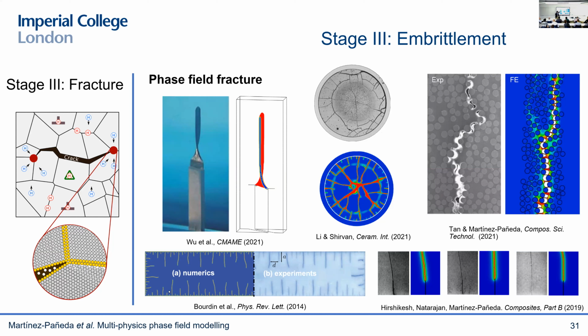You can see here multiple examples, some from my group, some from other groups, where very complex cracking phenomena can be captured and show a very good agreement with experiments. And we have had quite a lot of fun through the years working on this. So we developed new phase field formulations for functionally graded materials, for the micromechanics of composites, for shape memory alloys, for glaciology to predict iceberg calving, for carbon nanotube composites. So we're having quite a lot of fun over the past 4 years working on this area,